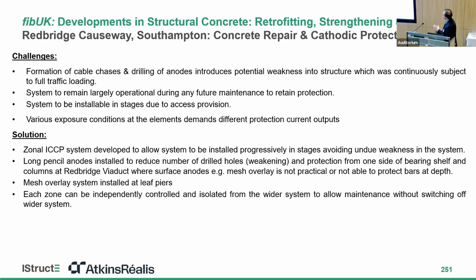First of all, as you can imagine, embedding all those anodes and cables within the concrete, to be chased or even surface mounted, is a challenge. And breaking out the concrete chases to embed them typically tends to cause weakness in a structure. So that's the challenge that we need to face.